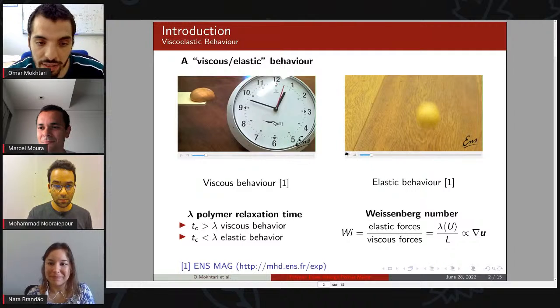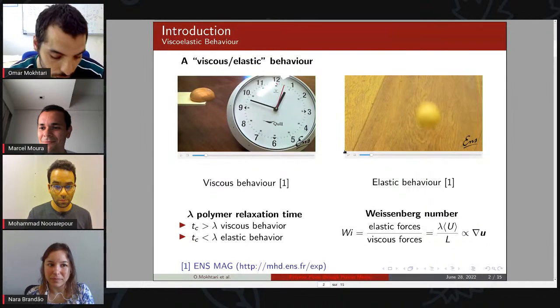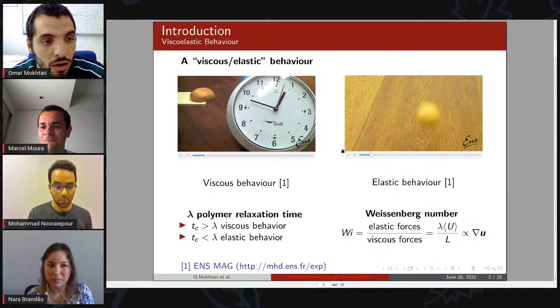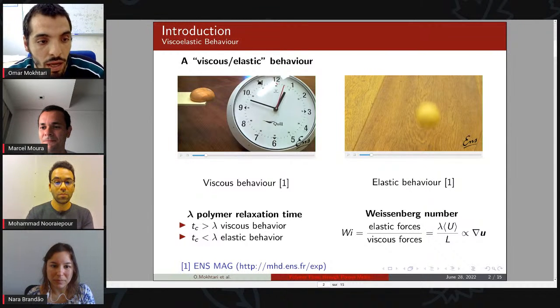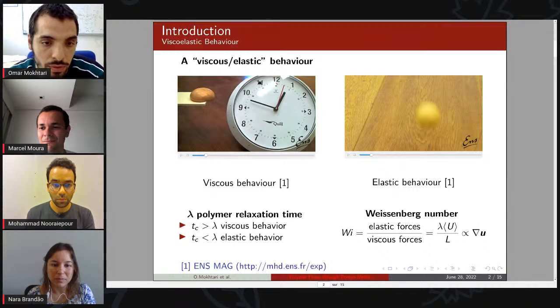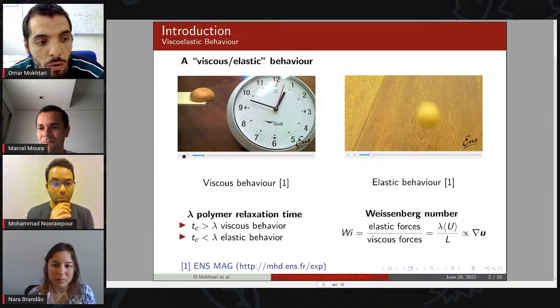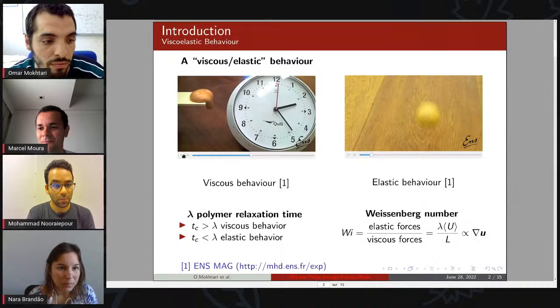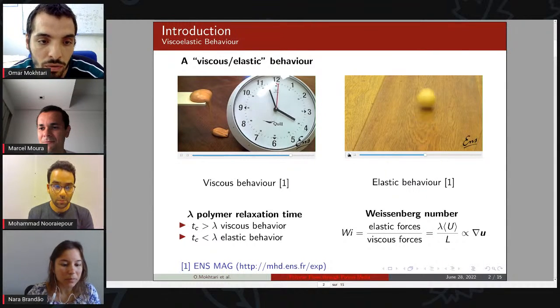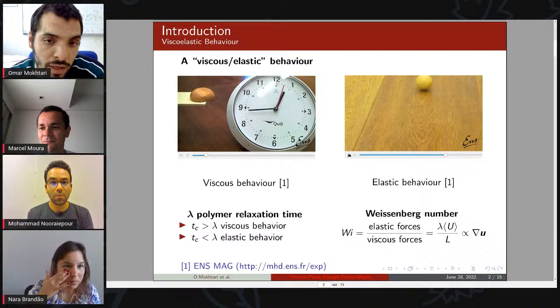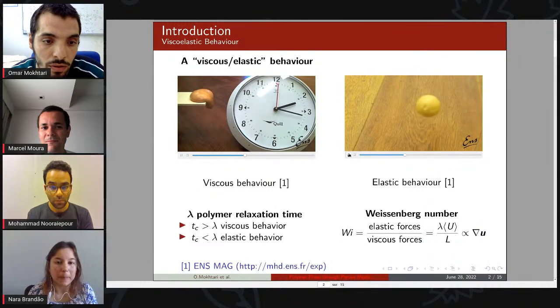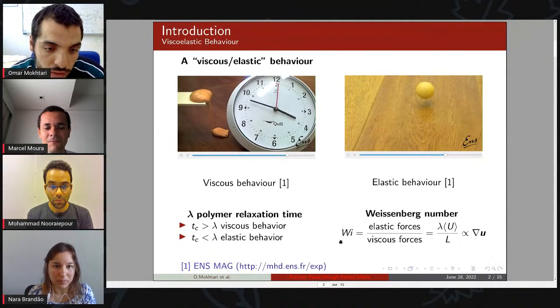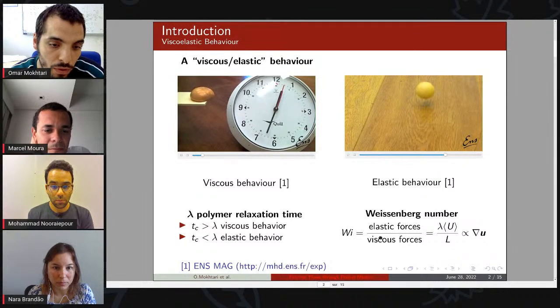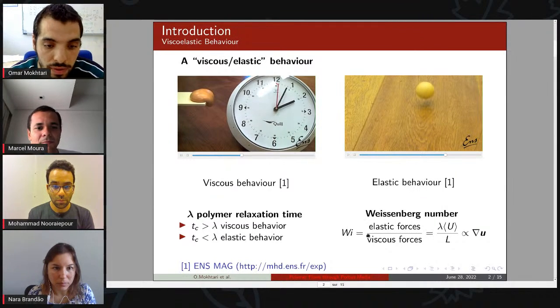Polymer solutions are generally used in groundwater remediation or enhanced oil recovery, and this is a viscoelastic material with behavior between viscous and elastic, depending on relaxation time lambda. When the time of solicitation is greater than lambda, the polymer solution has a viscous behavior, and when the time of solicitation is smaller, the behavior is elastic. This can be characterized by the Weissenberg number, which is the ratio between elastic and viscous forces.